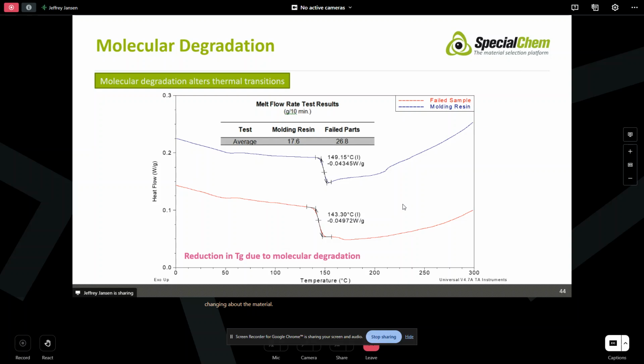A good chance it's going to be molecular degradation. They've either been degraded during the molding process or during field service. We did a melt flow rate to come back, and we found that was in fact the case. Much higher melt flow rate on the failed parts, which correlates with that reduction in the glass transition. So we can look for changes in the glass transition or the melting point to give us some information about potential degradation.